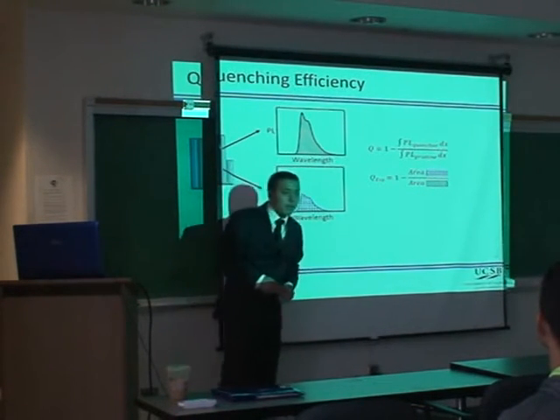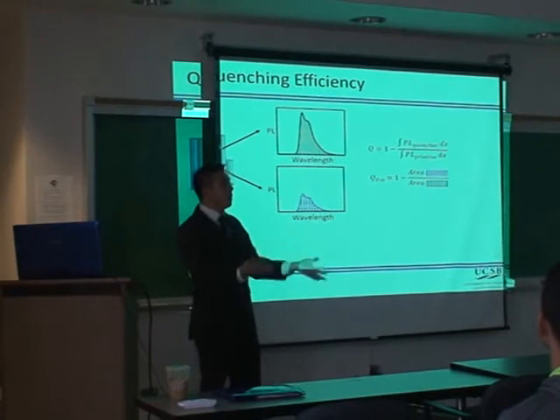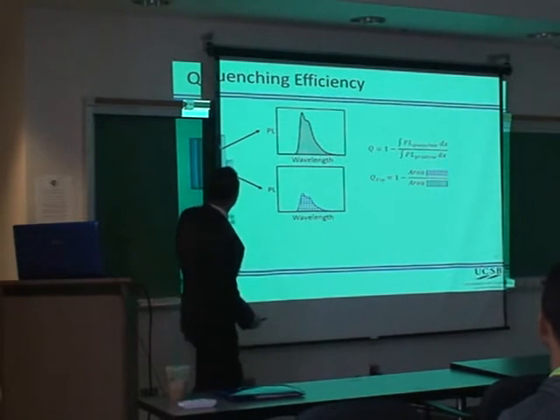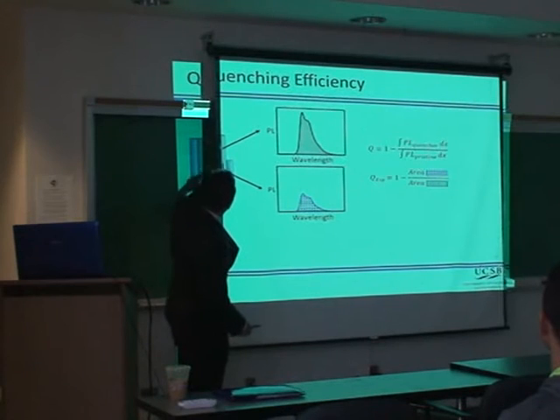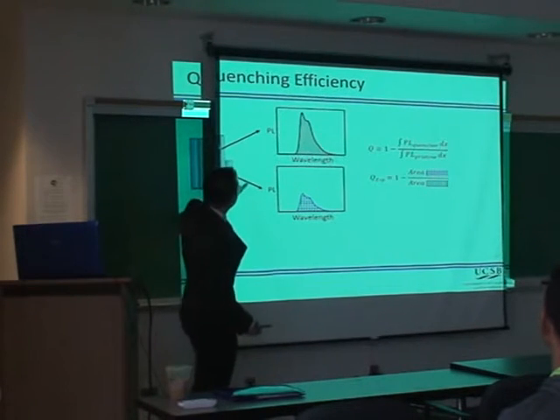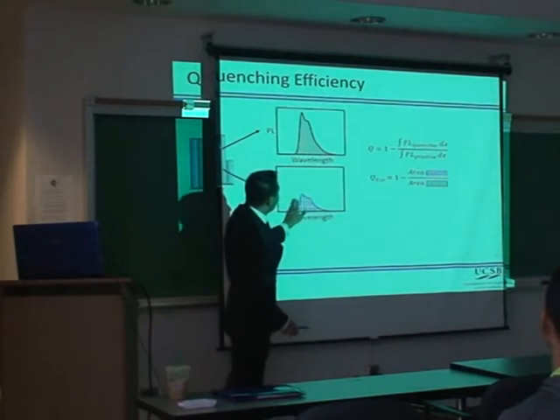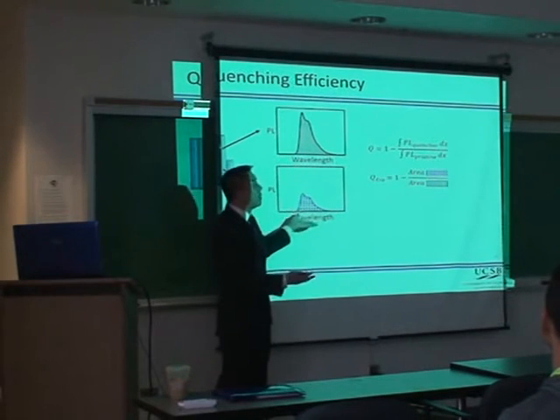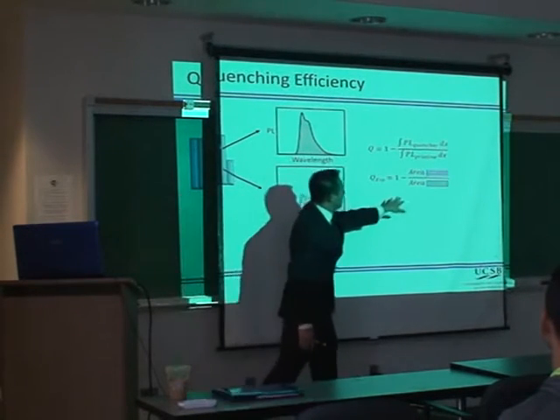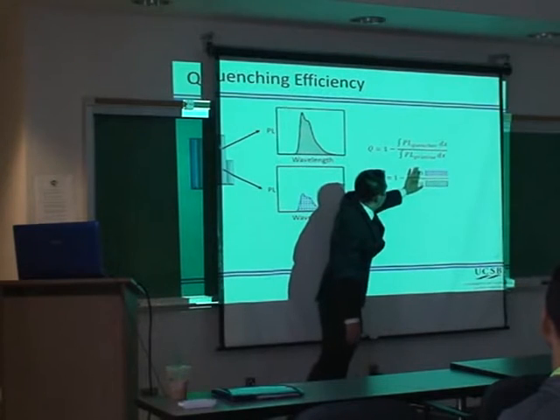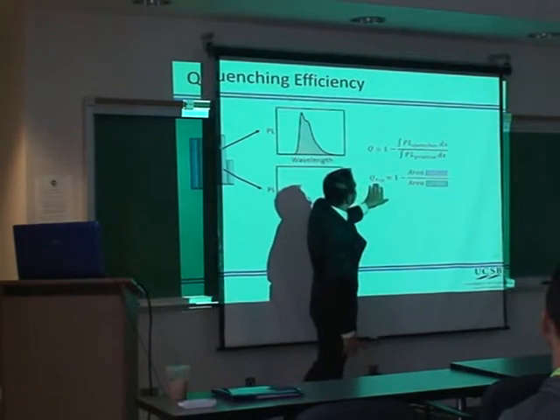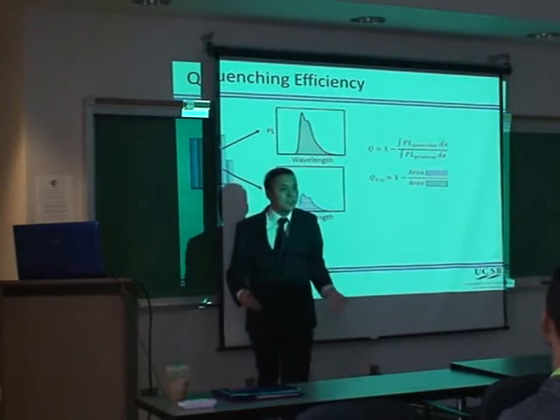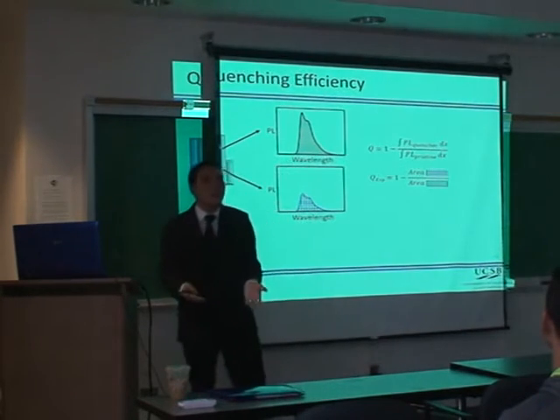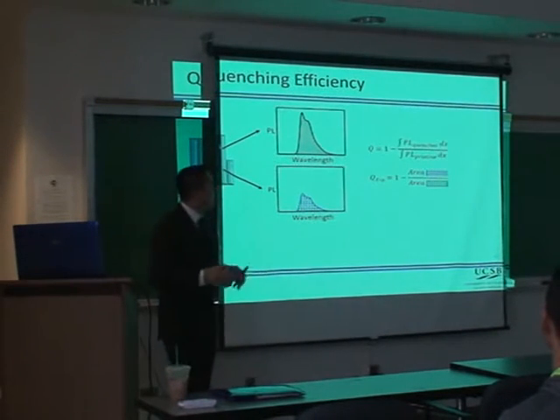So let's say, for example, you had a material that had a very, very long exciton diffusion length. In this case, all the excitons generated on the side with the quencher will be quenched, and your photoluminescence from here will be very diminished, because none of them are emitting, they'll all be quenched. And in this case, this whole thing would approach 0, and our quenching efficiency would be 1, basically. So higher exciton diffusion length, higher quenching efficiency. And that's how the two are connected.